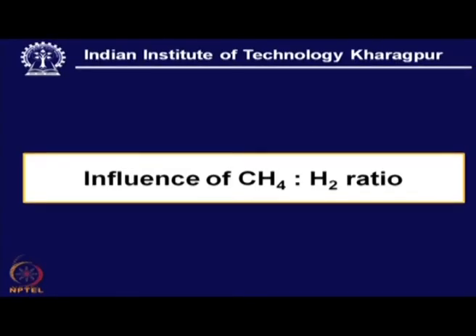Influence of CH4 to H2. This is a very important consideration. Now, CH4 concentration means a higher percentage of carbon. So, we have more carbon available for the growth of the coating. However, it is found that if we have too much methane in proportion to hydrogen, we may end up with